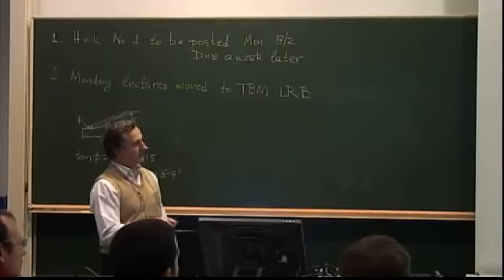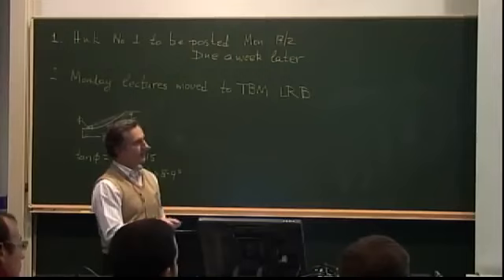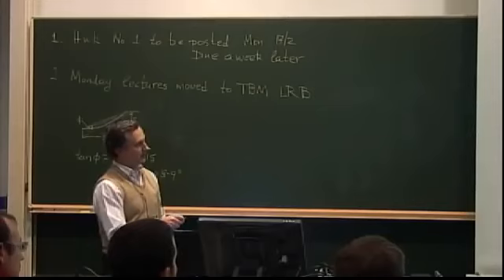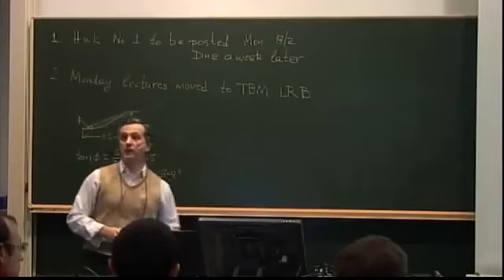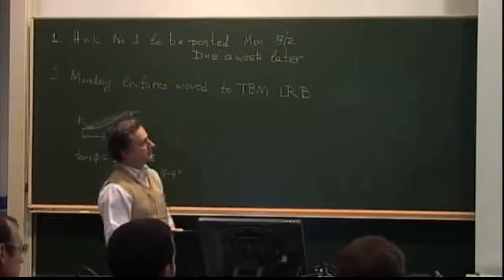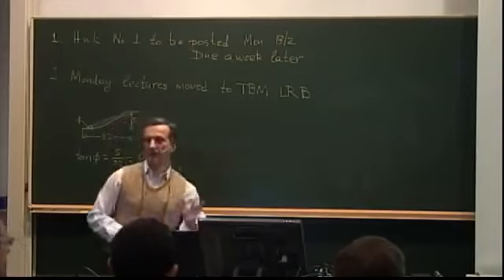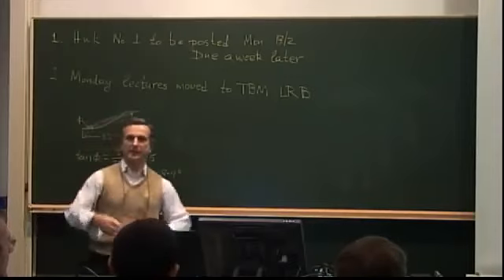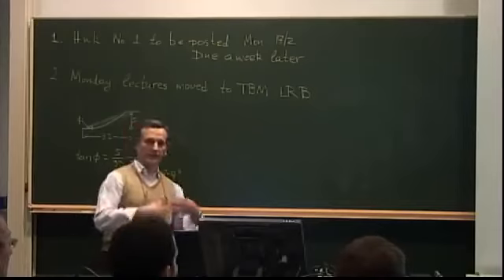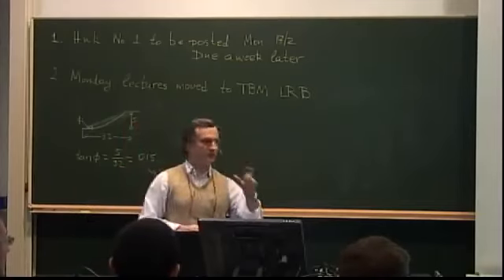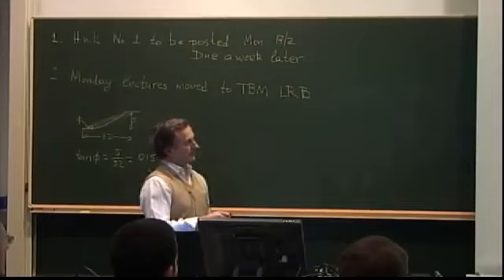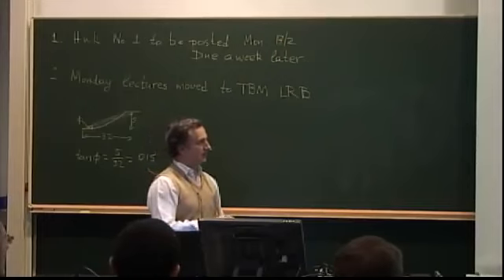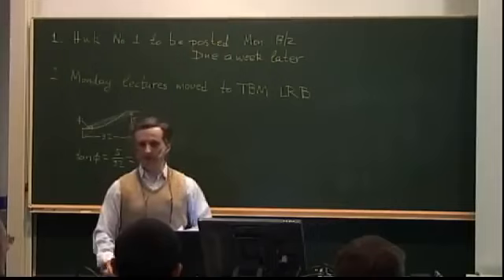The shear stress is 0 here, but it increases to a very high value because it tries to transfer all this load that was originally here, and then comes down to 0 because at the same time, the load in the fiber starts from 0 and increases to the far field value some distance away, which, by the way, is about 10 fiber diameters. It takes about 10 fiber diameters to appear as if there's no crack, because if the load in the broken fiber is back to its full strength within 10 fiber diameters, then only within those 10 fiber diameters something serious is happening.